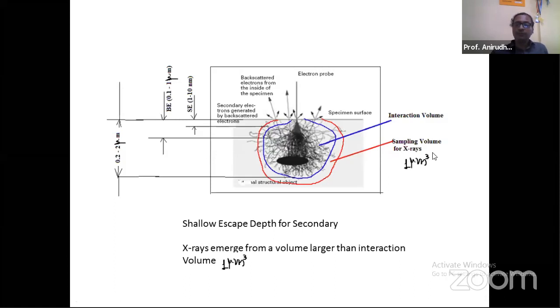So if you are trying to differentiate between two elements, two different zones from your matrix, then at least they should be of reasonable size. Reasonable in the sense that you cannot achieve a resolution which is better than this 1 micrometer cubed when you are trying to identify elements using your EDS.